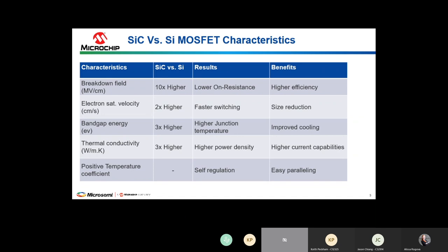Comparing some of the characteristics of silicon carbide versus regular silicon: the first thing is the bandgap energy — the energy required to get electrons flowing. In silicon carbide it's generally about three times higher than silicon, which is why we call these products wide bandgap. Because it takes more energy to get electrons flowing, performance at higher junction temperatures is much better, meaning you can run these products at higher junction temperatures with less stringent cooling requirements.